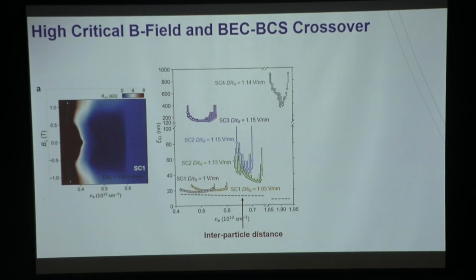Okay? And there's another very unusual feature. If you apply out-of-plane magnetic field, you can ask, how high a magnetic field would I need to eventually kill the superconductor, let's say SC1? Because eventually you have to kill it, due to orbital effect, right? This is the out-of-plane magnetic field. And it turns out the critical field is almost 1 Tesla, which is a crazily high number for a superconductor that has a TC of only 200 millikelvin.